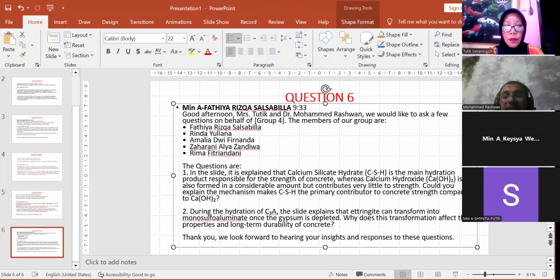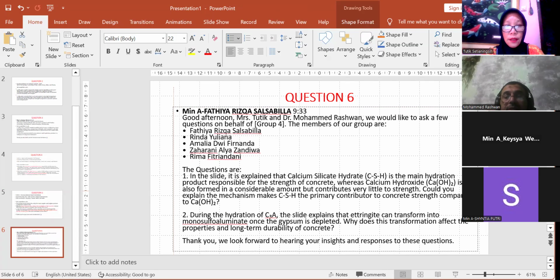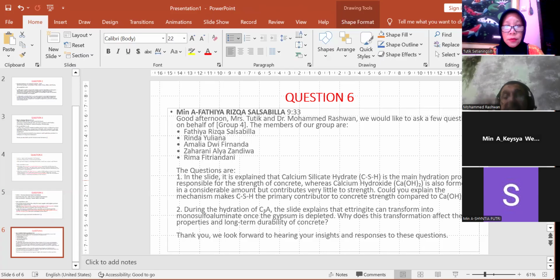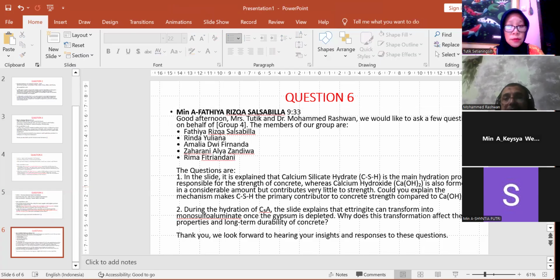This is the problem. This is the catastrophe. Why? Because when the cement is hardened and ettringite is produced, ettringite has in its structure 32 mole of water. Do you imagine 32 mole of water? This water causes expansion in the hardened concrete, and this can make cracks in the concrete and increase the porosity, increasing the penetration of other deterioration agents like sulfate and chloride, especially in seawater.